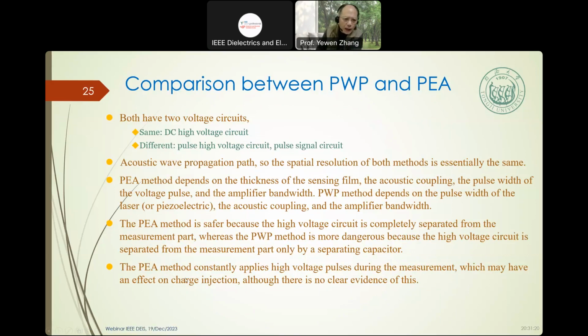Both have two voltage circuits. It's the same applied DC voltage circuit, but they're very different. For PEA, there is a pulsed high voltage circuit, and for PWP it is a pulsed signal voltage. The acoustic wave propagation path is the same, so the spatial resolution of the two methods is essentially in the same order. The PEA method depends on the thickness of the sensor film, usually PVDF, the acoustic coupling, the pulse width of the applied voltage pulse, and amplifier bandwidth. The PWP method depends on the pulse of the laser or piezoelectric, acoustic coupling and amplifier bandwidth.